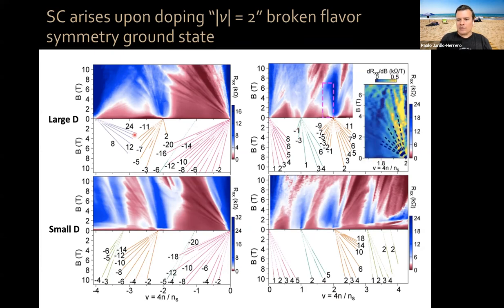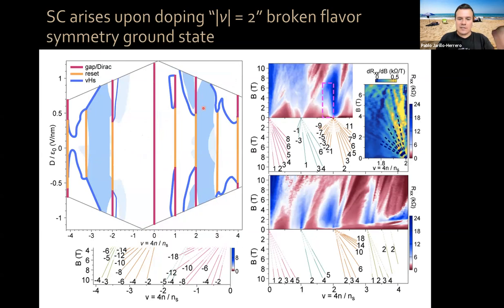The most important key thing that gave us information about this was in this region close to filling factor two, this region two minus delta, where we saw the Shubnikov-de Haas oscillations pointing towards charge neutrality, indicating that this is a hole Fermi surface. So this corresponds to this region where we see superconductivity. What this is telling us is the following.